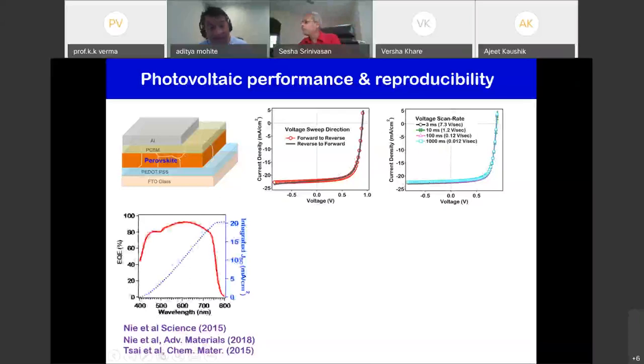We were able to get a nice quantum efficiency. You'll see that the quantum efficiency as a function of excitation wavelength is more than 80% or 90% at all times. And you can integrate this to get your short circuit current, which is about 20 milliamps per centimeter squared.